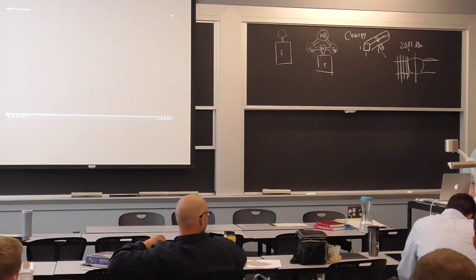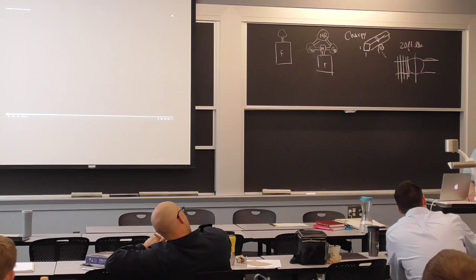When it's a really big problem, there are people who actually want to know how to solve it first, and then they'll worry about how they divvy up the liability and the cost. Okay? So it turns out they ended up developing jointly an electrical resistance measuring device, a non-destructive probe that you could just put on the surface. I actually have one that costs about $5,000, and you just put it on the surface of the aluminum. You measure the electrical resistivity of the aluminum, and you can tell what the heat treatment is, okay, for certain alloys. And so that was developed under that program, so they could go and check the wings at lots of locations to see if they had a bad piece of plate.